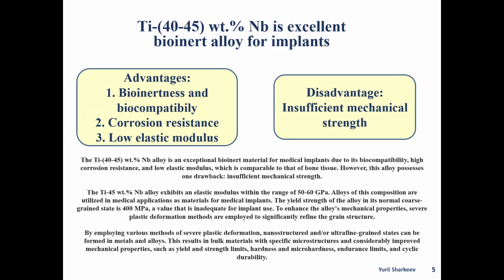for implant use. To enhance the alloy's mechanical properties, severe plastic deformation methods are employed to significantly refine the grain structure. By employing the methods of severe plastic deformation, nanostructured and/or ultrafine grain state can be formed in metals and alloys. This results in bulk materials with specific microstructures and considerably improved mechanical properties such as yield and strength limits, hardness and microhardness, endurance limits, and cyclic durability.